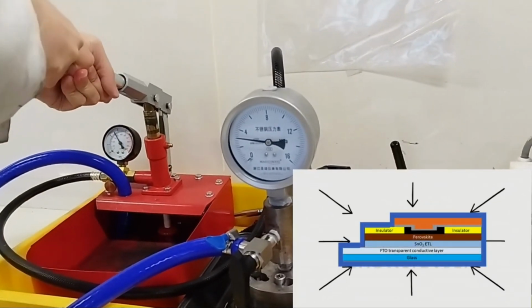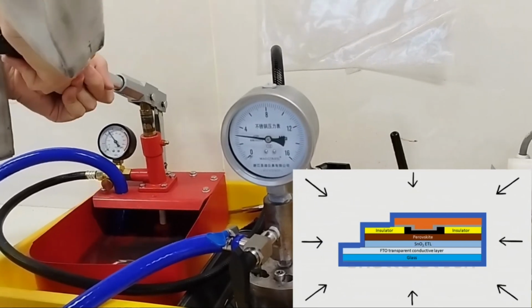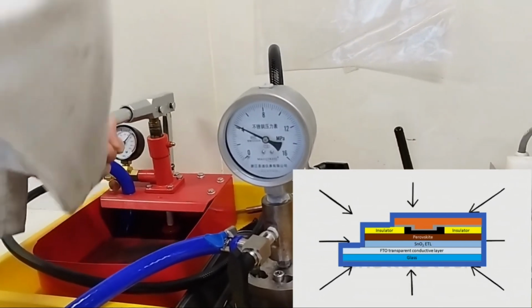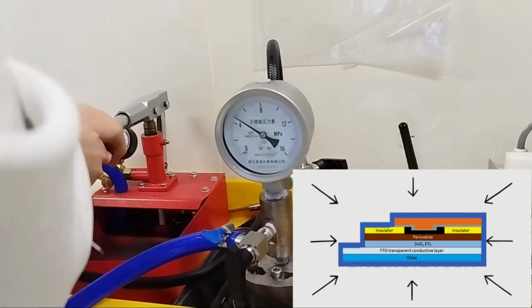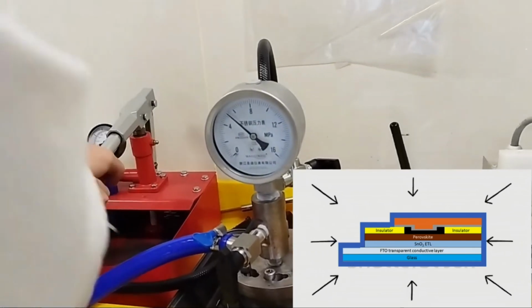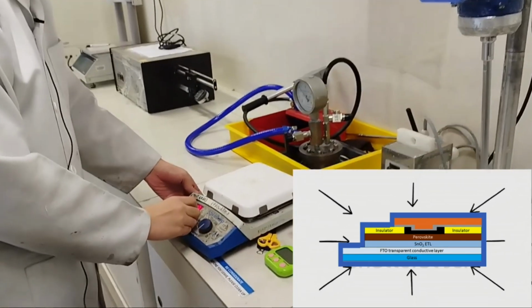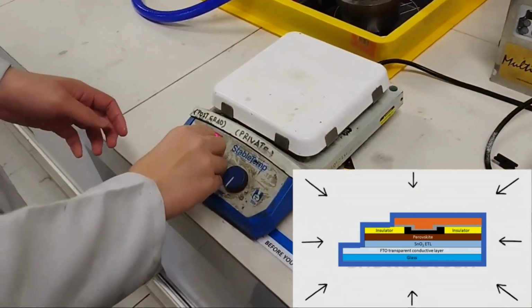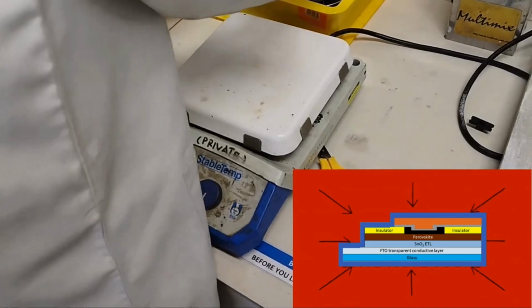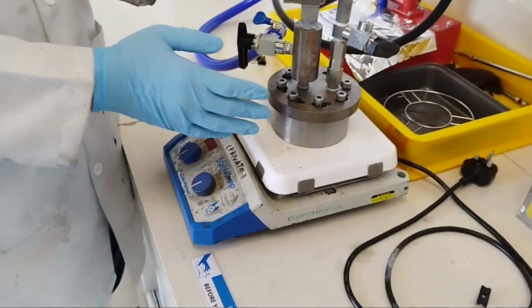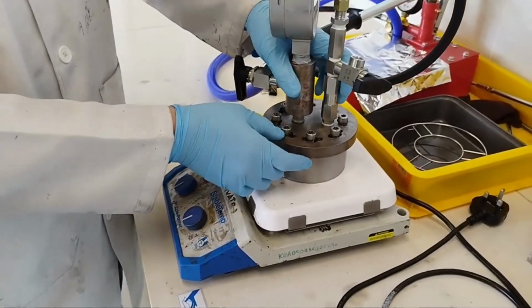This high isostatic pressure environment will compress the carbon electrodes evenly onto the surface of perovskite film, without fracturing the glass substrate. The chamber was then placed on a 100 degrees Celsius hot plate and heated for 10 minutes. Afterward, I depressurize the chamber, and the sample is ready.